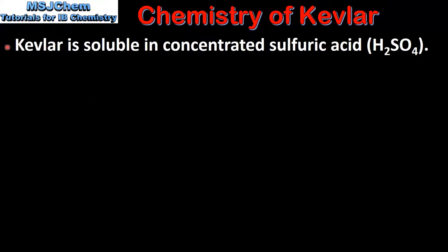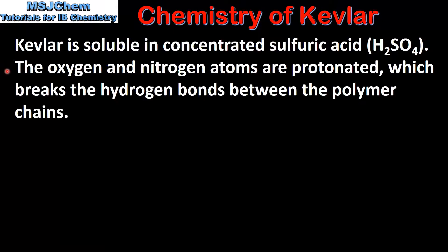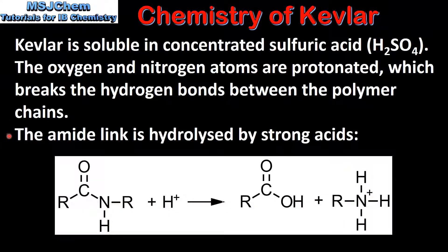Kevlar is soluble in concentrated sulfuric acid. This is because the oxygen and nitrogen atoms are protonated, which breaks the hydrogen bonds between the polymer chains. The second reason is that the amide link is hydrolyzed by strong acids.